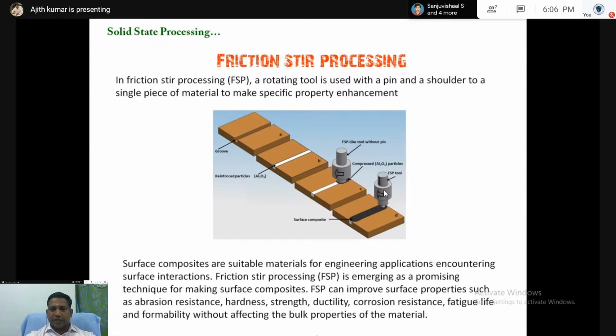Then friction stir processing. This is a selected area composite making process. This is friction stir processing. One rotating tool will be there. If you want a composite in a particular area, that means in the white region, initially we make a groove. On the groove, we put the ceramic or any reinforcement particle we want. That particle we fill in. After that, with the rotating tool, we carry out friction stir processing. By this friction stir processing, we can make the composite in the particular area.